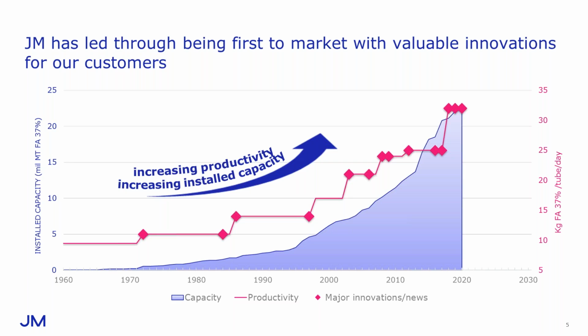This has been done by, for instance, increasing the gas flow in the process. We introduced recirculation to reduce the oxygen concentration in the gas phase, because that enabled us to increase the methanol concentration that is used to oxidize into formaldehyde. If the oxygen was decreased, we were avoiding being in the flammable region between the oxygen and the methanol. But of course, we have also worked very hard and dedicated to improve and adapt the catalyst, because it needs to handle an increased methanol concentration and with that increased activity. So we need a stronger catalyst to avoid that it's degrading or falling apart when it's exposed to higher production.